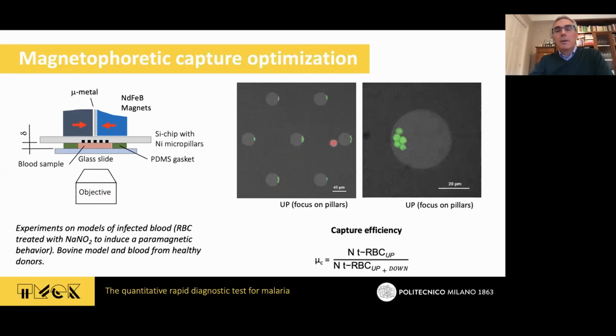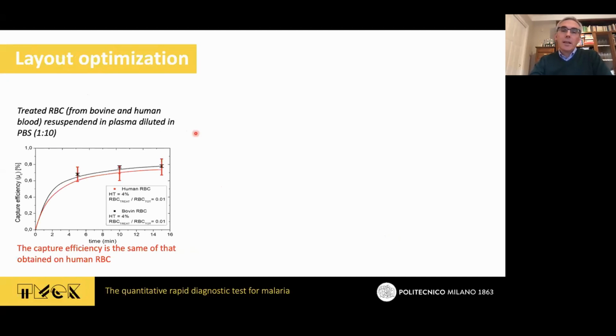Here you see the typical configuration of treated red blood cells, say magnetic red blood cells, attracted by the nickel micropillars, and this is just a zoom. In this way, we were able to follow the capture of the particles over time and estimate the capture efficiency, which was defined like this: the number of treated red blood cells which are captured, seen when you focus exactly at the surface of the nickel micropillar, divided by the total number of particles in the field of view, those placed here and those placed at the bottom of the cell, which means at the surface of the glass slide. And in this way, we did a sort of optimization.